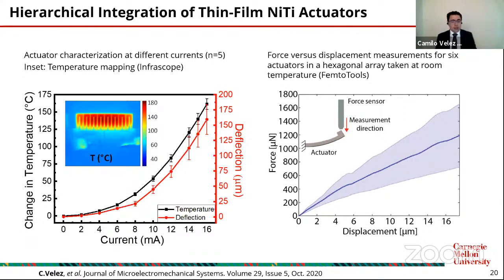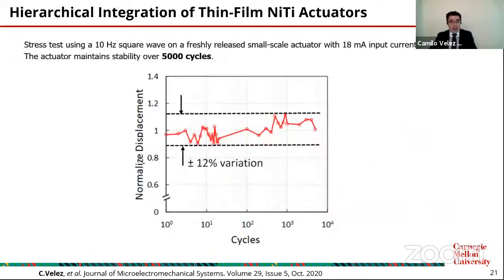And finally, you can measure the force on these devices. We use a Femtotools sensor. It's a direct force measurement, a capacitive sensor that moves a tip, and physically you're measuring the force on the actuator. And you can find that you are getting displacements up to 17 microns, and forces in general up to 1,200 micronewtons. So those are micronewton scale forces that you can actually use in a micro robot to win a competition at some point, made out of microfabricated and 3D printed actuators.